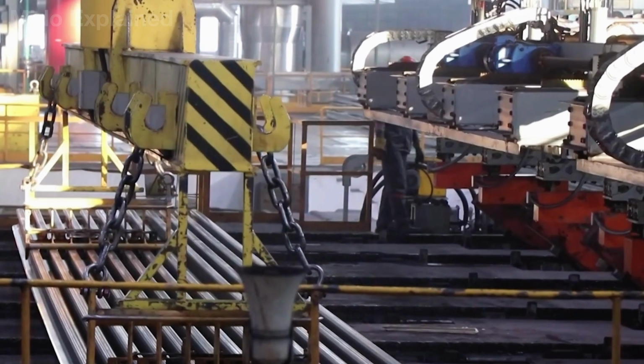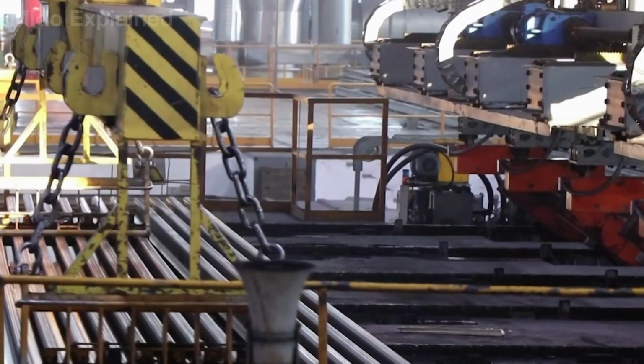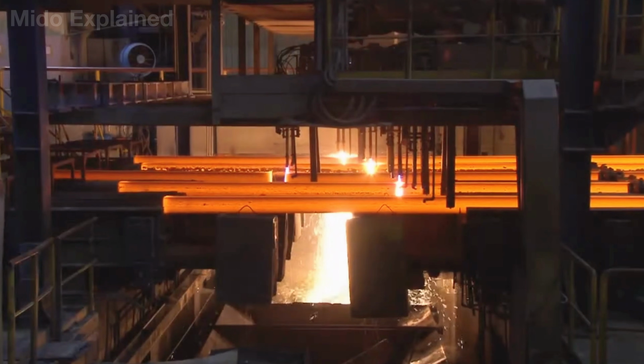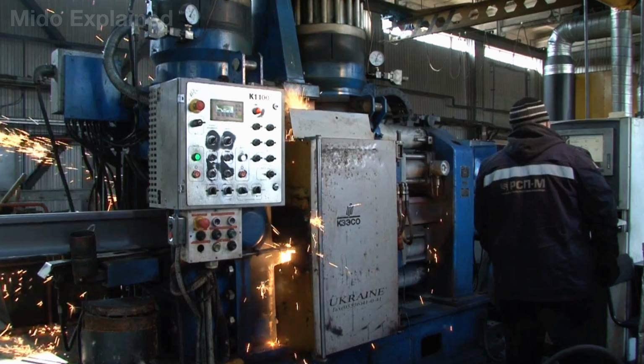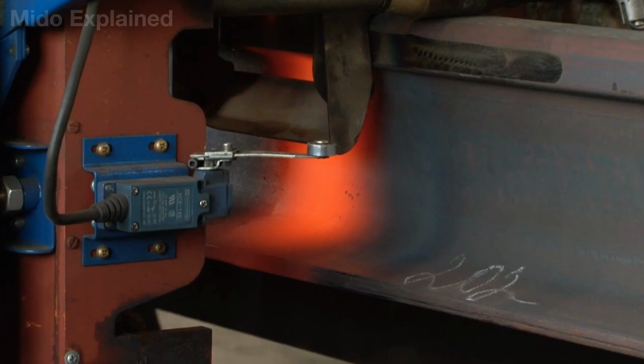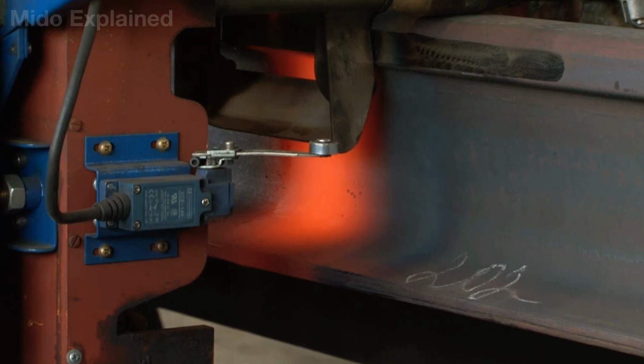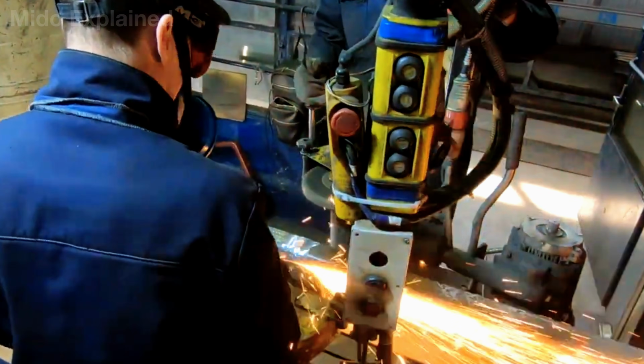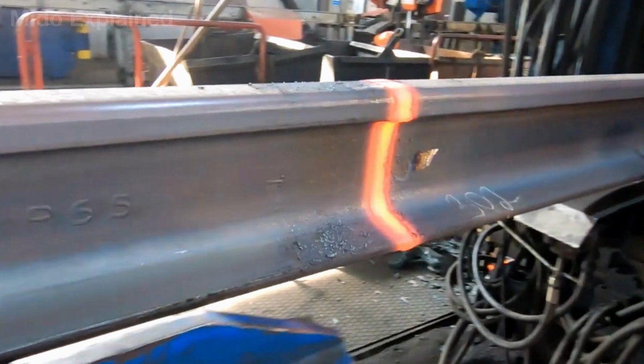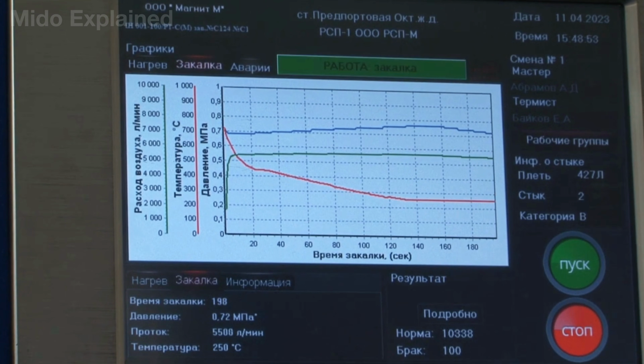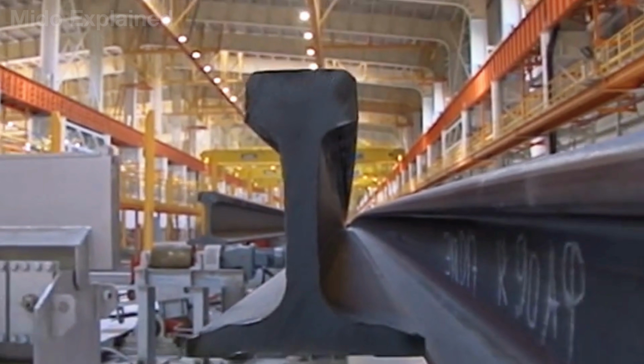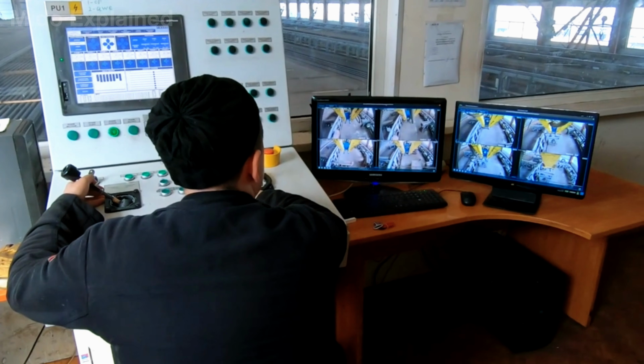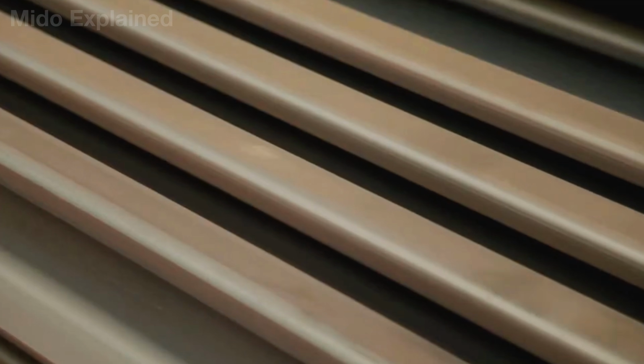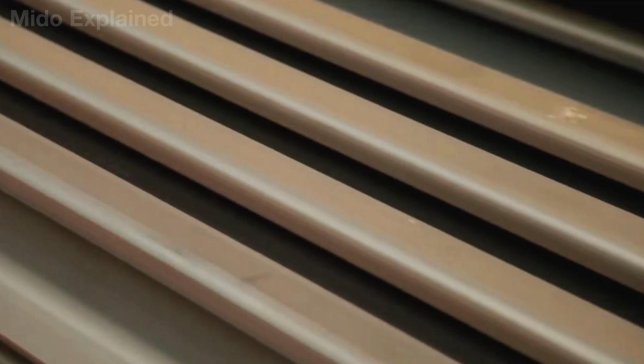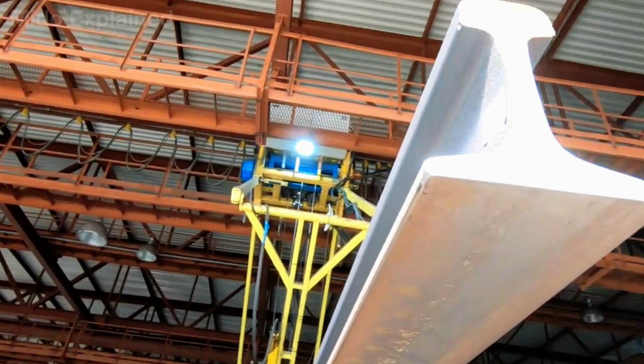After the heat treatment process is complete, the rails are moved to the welding area to form continuous long rail sections. Here, a roller system precisely positions the two ends of the rails before they are joined together. Under the influence of extremely high temperatures and strong pressure, the metal at the joint melts and fuses into a single block. Any excess material generated during welding is immediately cut and ground away to ensure a smooth surface. The entire process is tightly controlled to ensure that the weld has the same strength and load-bearing capacity as the original steel of the rail.